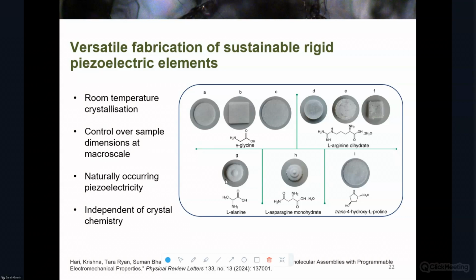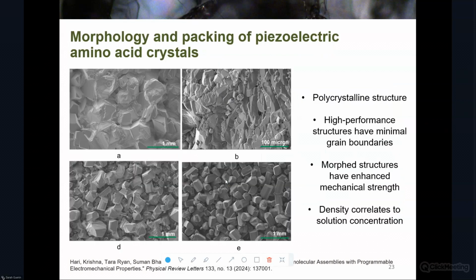which then allows you to do things like coat them, electrode them, and use them for applications. Because if we want to phase out ceramics, we have to get to the point where you can essentially take the PZT element out of whatever device application and perfectly replace it with this molecular crystal alternative. And all of these showed a measurable piezoelectric response as well without poling. So for ceramics, we need to apply a really high electric field to align the dipoles to maximize the response. But once we semi-orientate our crystals in our assembly, we don't need to pole them because of that naturally occurring dipole. So under the SEM, this is what they look like. If you've seen a ceramic under an SEM as well, you'll see that these do look quite similar, which is also exciting.